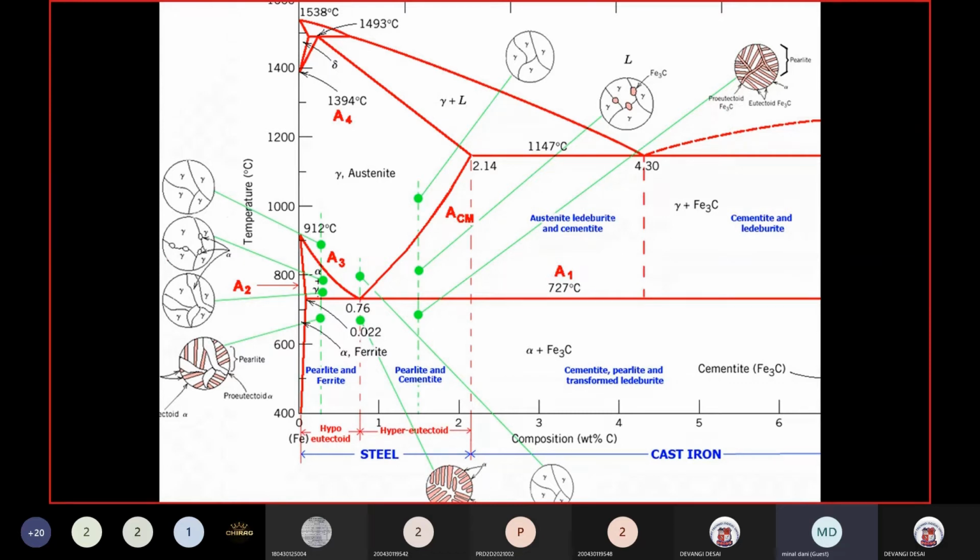तो you have to take the cycle, you have to add 30 to 50 degrees Celsius more for selecting the heating temperature. So it will come around 870 880, right. So you have to heat your EN8 steel above 880 degrees Celsius, then and then your austenite will come.